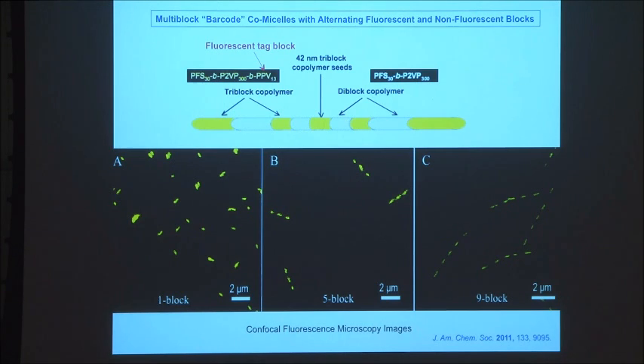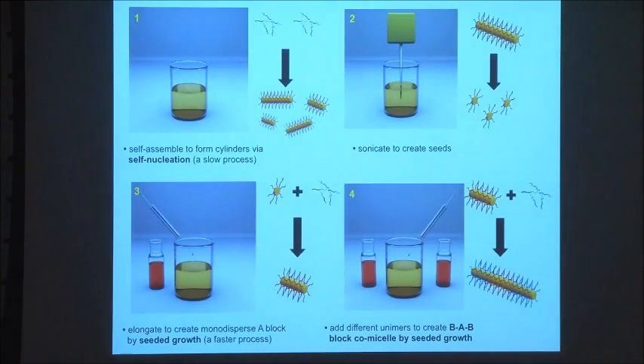So how do you do this in the lab? It's very easy to do, and you can do it using wet solvents in air and in the fume hood. So initially what you do is you take the block copolymer and you dissolve it in a little bit of common solvent, THF, and then add hexanes, which is selective for the coronal block, and you leave it for 24 hours, and this is a slow process that forms cylinders by self-nucleation, and you get cylinders of different length. You then sonicate these down. You just put a powerful sonicator into the solution and break these down into small seeds.